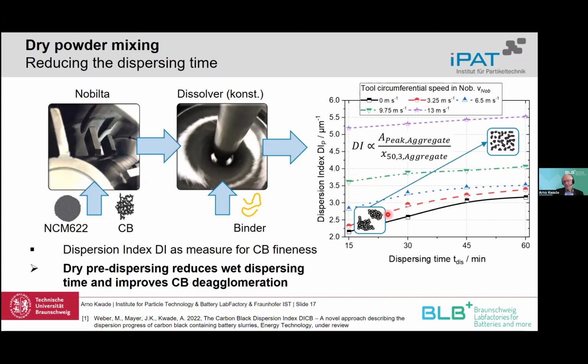And this is due to the disagglomeration of the carbon black agglomerates to aggregates. For example, if we have an optimum dispersion index of about 3.2, 3.3, you can see that we can reach this with a nice dry premixing in less than 15 minutes. If we have no premixing, then we need 60 minutes. But economically, you have to decide what is more important: having another process step, or taking much more time for the wet dispersing process.